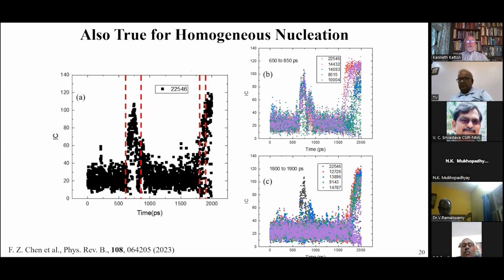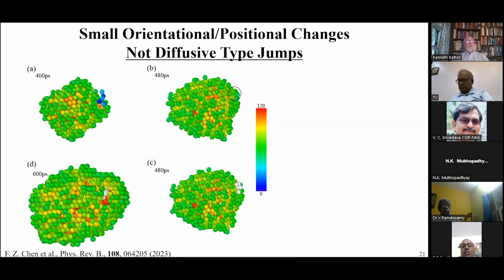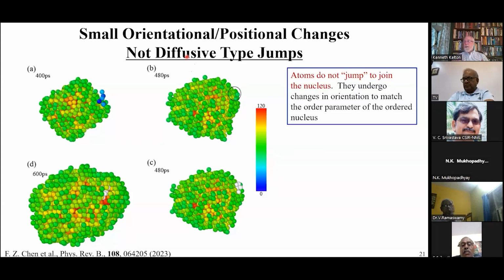So to illustrate that, here's a situation where these blue atoms are next to a cluster. They join the cluster. Here you can see that they're part of the cluster. Here I've labeled those atoms in white so you can see them. And they stay in the cluster, and then the cluster continues to grow, and so they're embedded in the cluster. When you look at how these atoms are joining, they're not doing it by diffusive jumps. They're doing it by changes in orientation to basically match the order of the crystal. So they're rotating, they're moving around a little bit, but they don't jump to join the cluster.